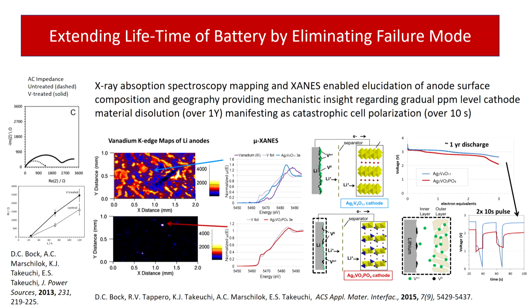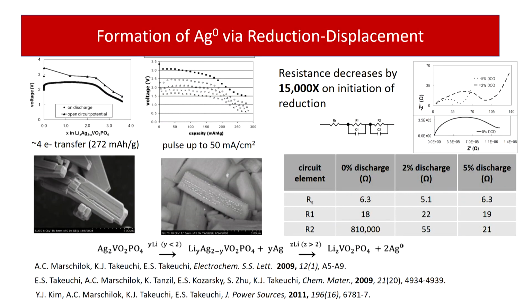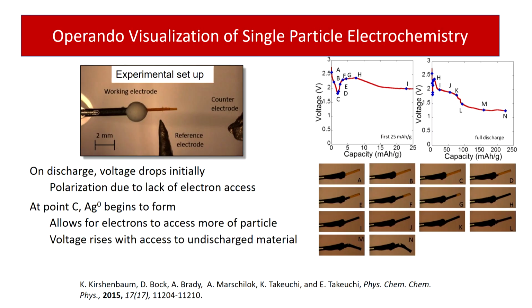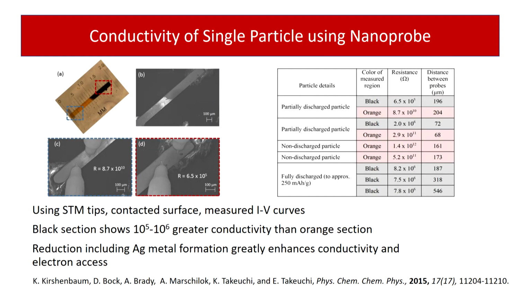We can demonstrate this by XAS and verify it by comparative pulse data after a very long discharge. So the phosphate material does, in fact, form silver metal. We can track this by SEM and XRD. There's profound change in conductivity on initiation of reduction. We can do this on a single particle. Take an individual particle, you view the active cell through an optical microscope, the reduction of the particle takes place, and then by using a nanoprobe measuring the local conductivity of a partially discharged section as well as a pristine section, we again see many orders of magnitude change in conductivity through partial reduction.